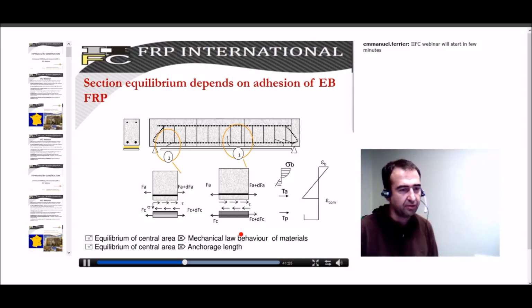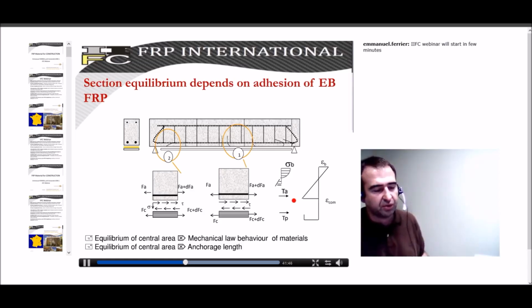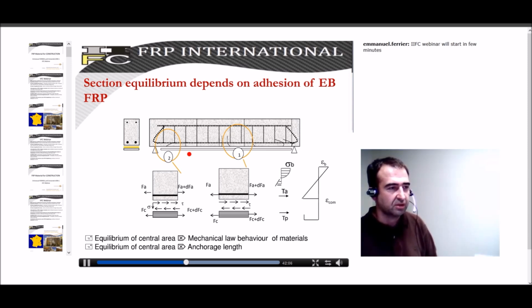So bond is important for a beam because when you strengthen a beam with FRP for flexure, for example, all of this can work if perfect bond adhesion between the FRP system and reinforced concrete is assumed. It means that you will have a continuity of strain between the steel, for example, and the FRP. Another important issue is that at the end of the FRP system, there is no debonding, because perfect bonding can be assumed in the central part, but if there is debonding of the laminate, the system won't work anymore. So the bond issue onto the concrete substrate is very important.